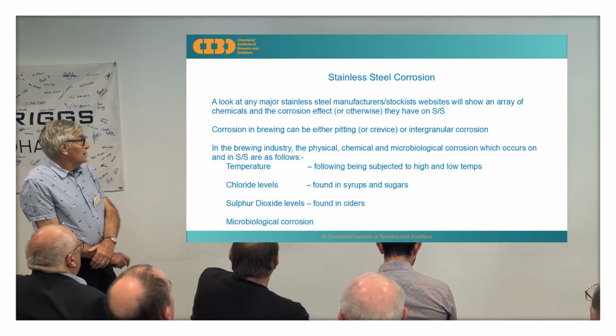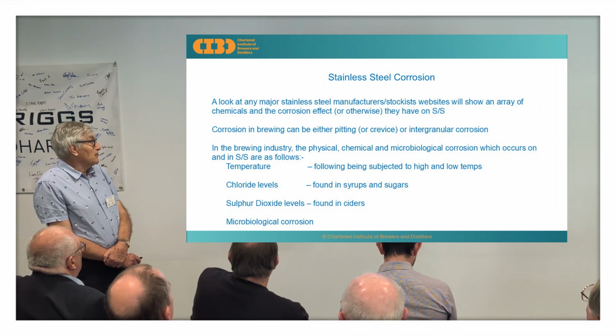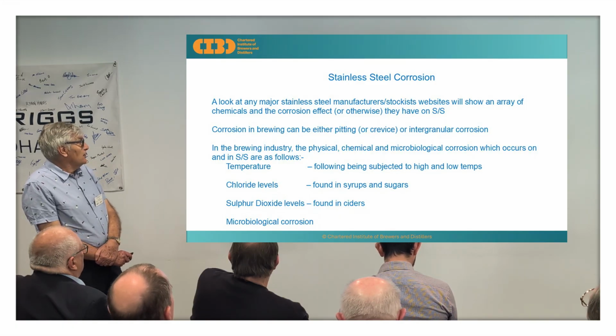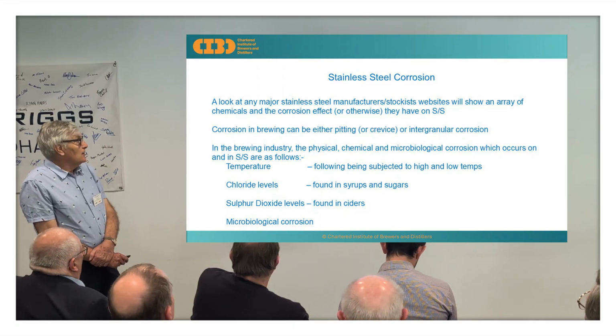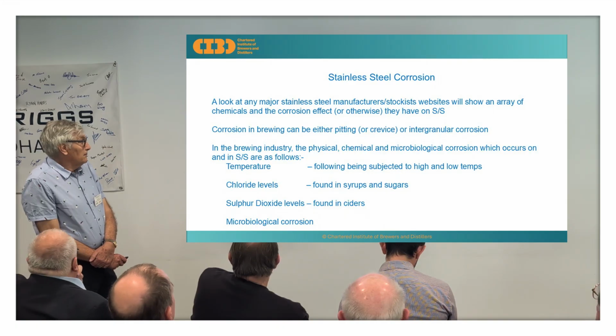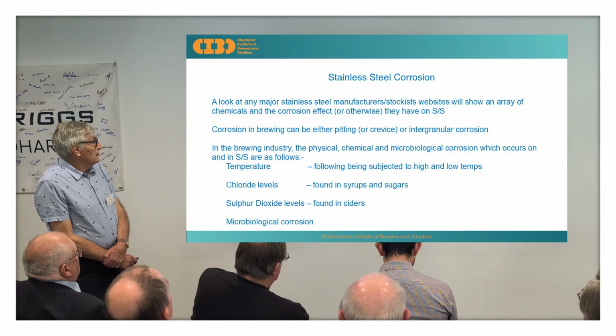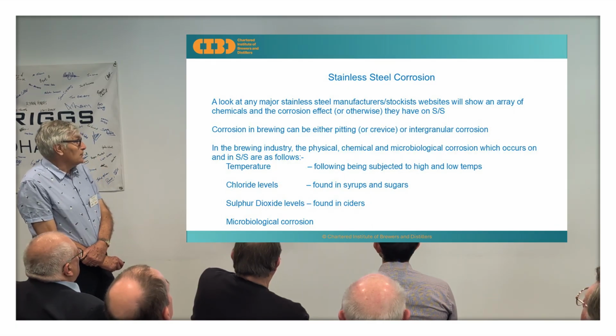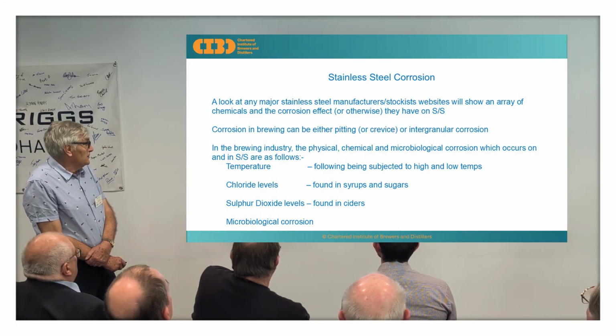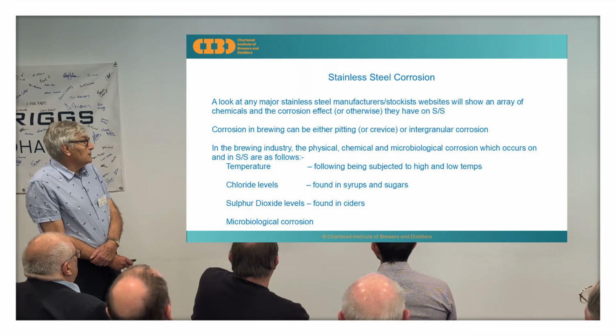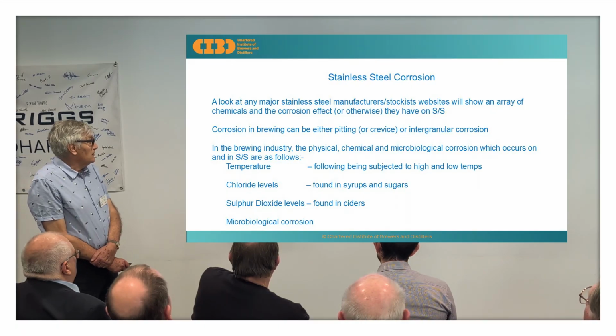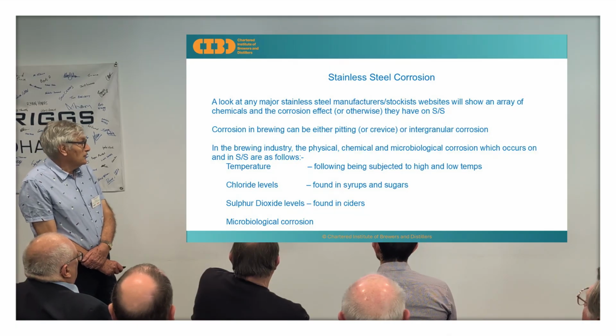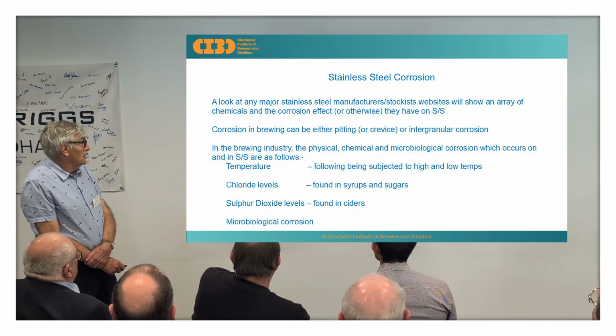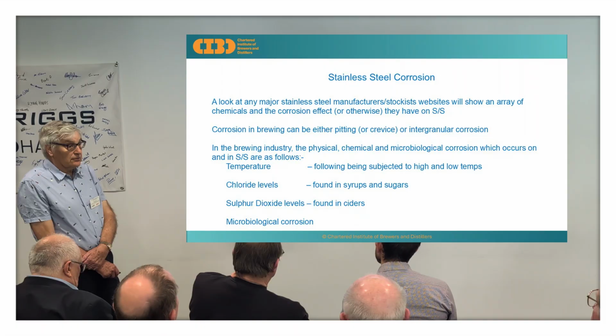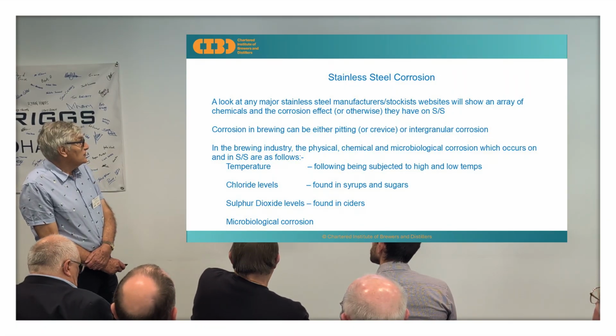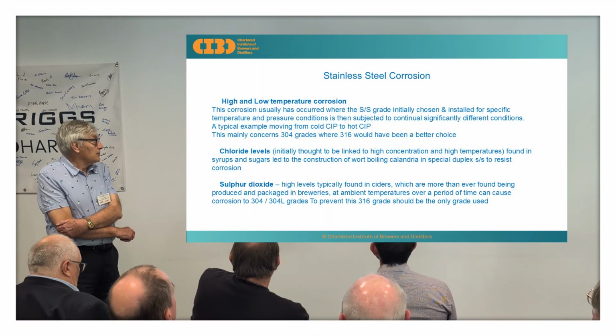Stainless steel corrosion. A look at the maintenance, say, on the stockist website shows an array, but in the brewing industry it's either pitting, crevice corrosion or intergranular corrosion. There are really three types of corrosion: physical, chemical, and microbiological corrosion, which occurs in stainless steels. One is temperature, following being subject to high and low temperatures. There's corrosion associated with the chemicals, which is the chloride levels found in syrups and sugars, and sulfur dioxide levels found in ciders. And there's one that I came across which was microbiological corrosion, with bugs eating the stainless steel, which sort of added them all. So, high and low temperature corrosion.